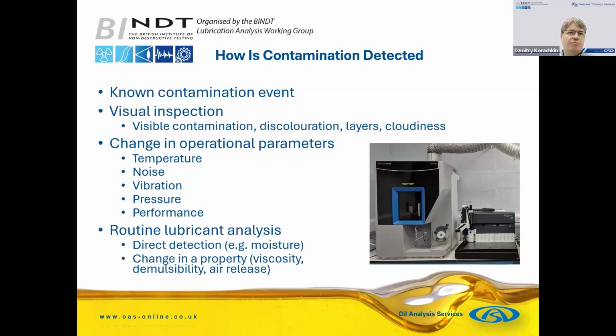And then another potential avenue is through routine lubricant analysis. Either the lab has detected contamination directly, for example, increase of moisture, increase of water content, or we notice the change in property, viscosity, or perhaps the demulsibility, air release, something that can be affected by contamination, and then we may want to investigate and find out what the actual contamination is, but we have detected its presence in an indirect way through a property change.